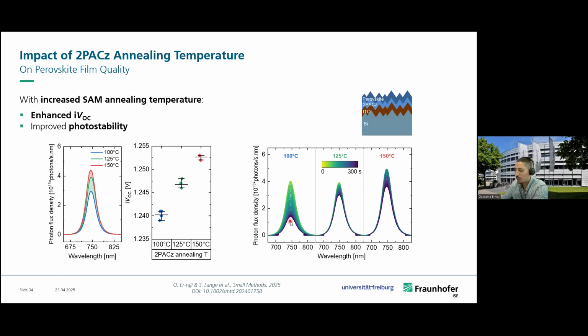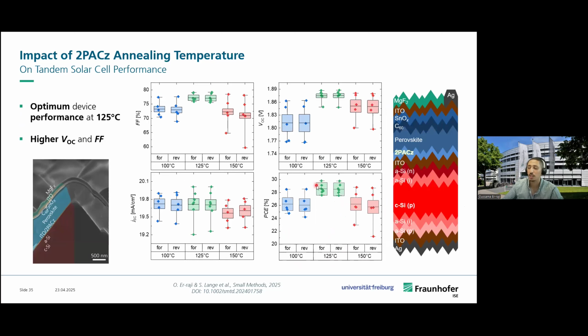So how was this reflected in tandem solar cells? Here again, 100, 125, and 150, and we were able to observe up to 1.3% absolute improvement in efficiency. And this was also reproducible from multiple batches, and this was mainly due to an improved fill factor, but more importantly, an improved VOC. And as a result, this was one of the first batches where we were able to have a 30% efficient cell with urea modified perovskite and 2PACz annealed at a high temperature.